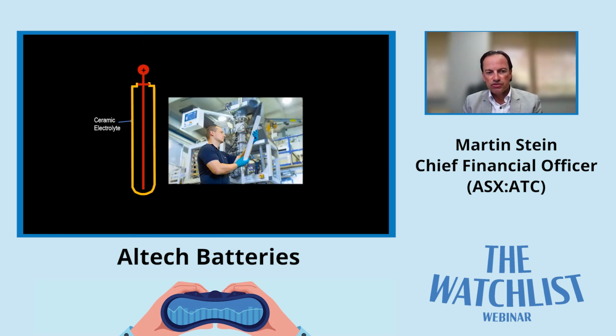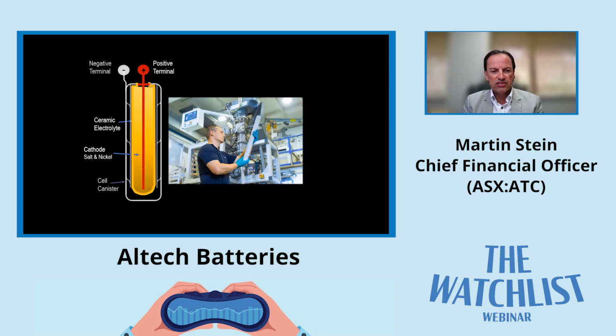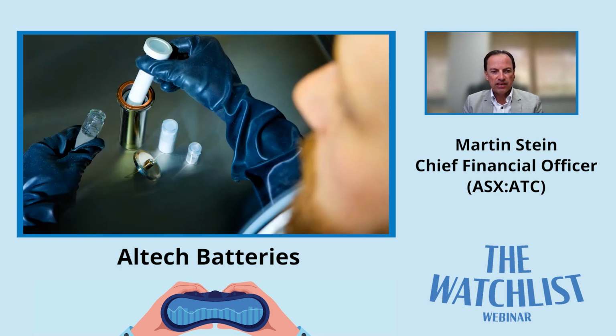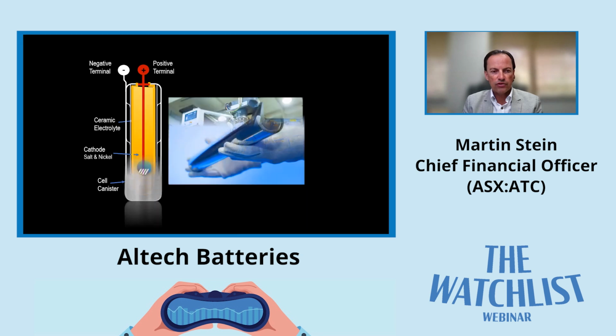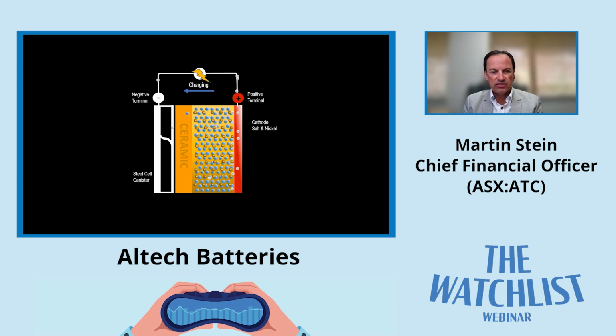So let's look at the chemistry here of how this battery works. So you see there the gentleman holding up the ceramic electrolyte. That ceramic electrolyte then has a positive terminal put inside of it, and then the salt, which is the sodium chloride, and nickel powder is put inside that ceramic electrolyte. And then that whole part with the raw materials in it sits inside a stainless steel canister, and the canister acts as the negative part of the terminal.